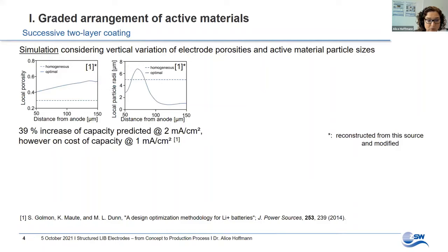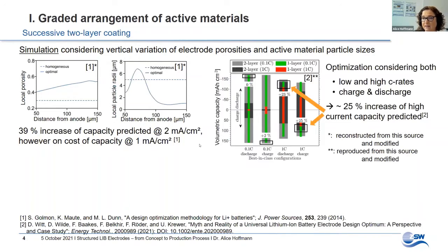The approach of two-layer coating is supported by results from simulation, considering a graded arrangement of porosity and active material particle size within the composite. In this study, we see an increase of rate capacity at 2 milliampere per square centimeter of nearly 40%, however at the cost of capacity. There is another study considering charge and discharge at low rate and at higher rate, where a 25% increase of capacity is predicted for the higher C rate without loss at low C rate.